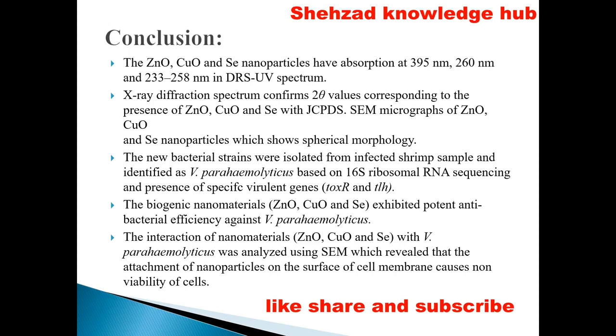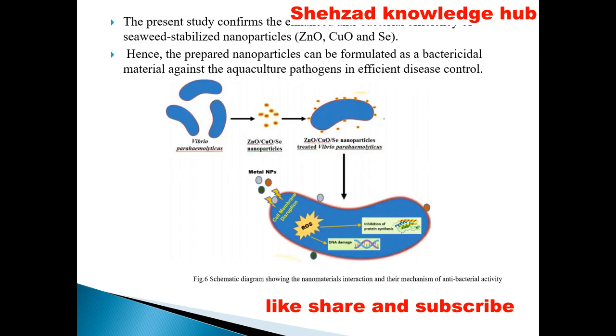The interaction of nanomaterials with Vibrio parahaemolyticus was analyzed using SEM, which revealed that the attachment of nanoparticles on the surface of the cell membrane causes non-viability of cells. The present study confirms the enhanced antibacterial efficiency of seaweed stabilized nanoparticles, which are zinc oxide, copper oxide, and selenium. Hence, the prepared nanoparticles can be formulated as a bactericidal material against aquaculture pathogens for efficient disease control.